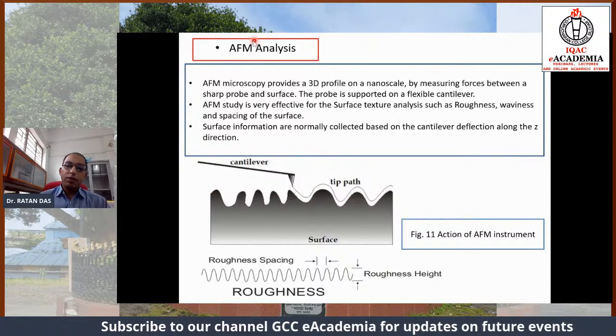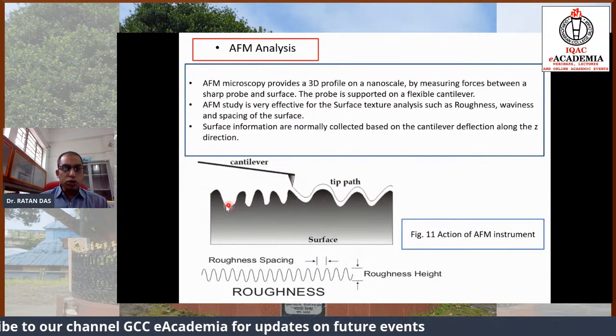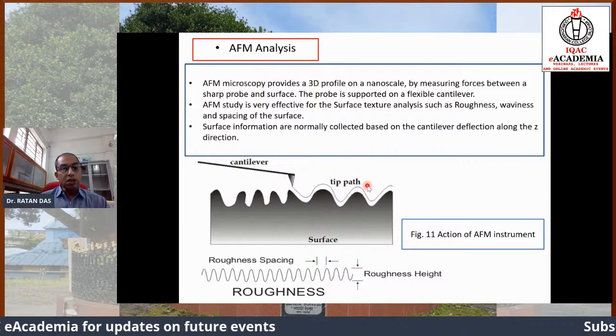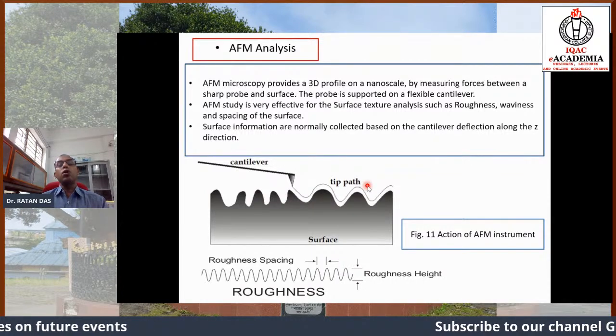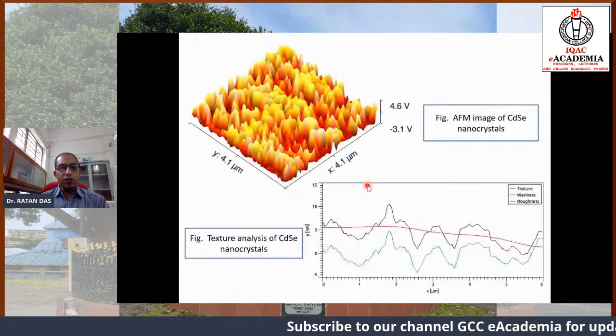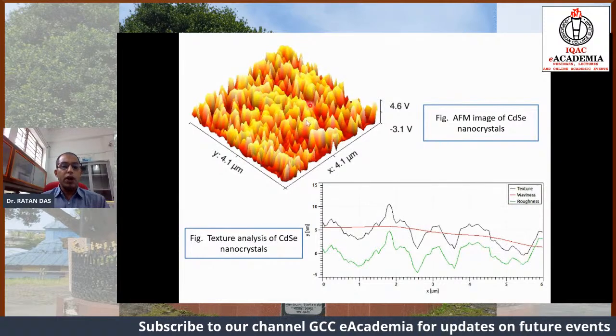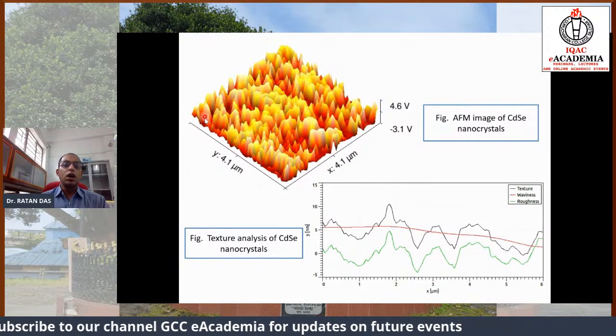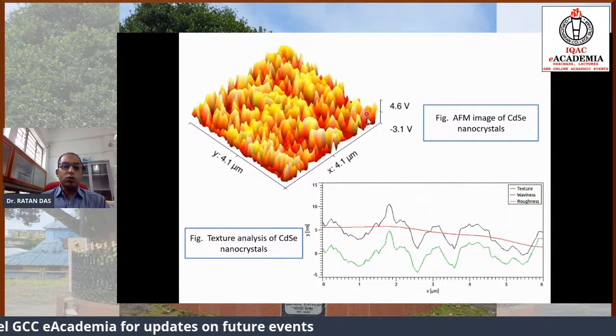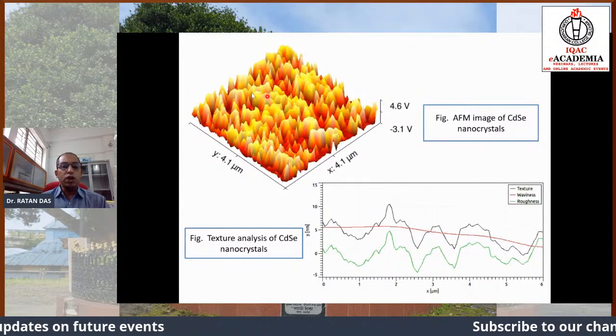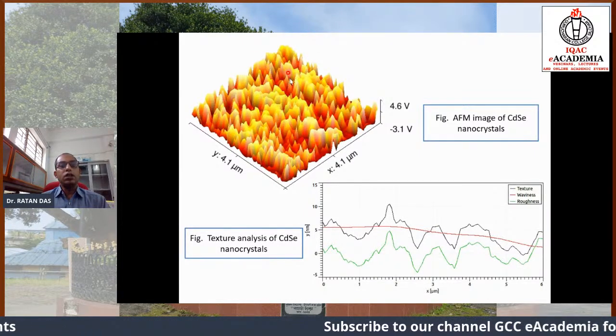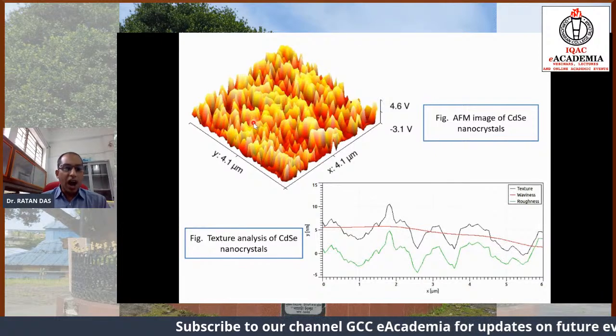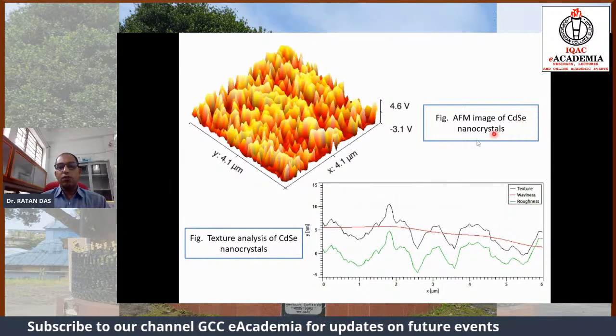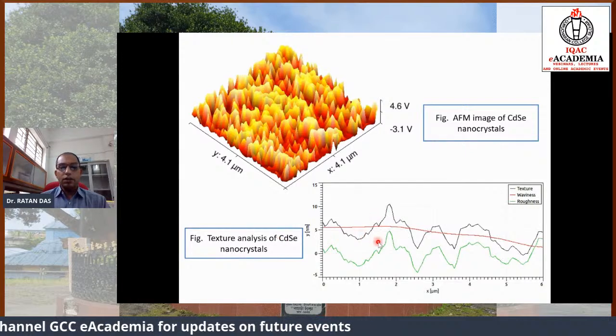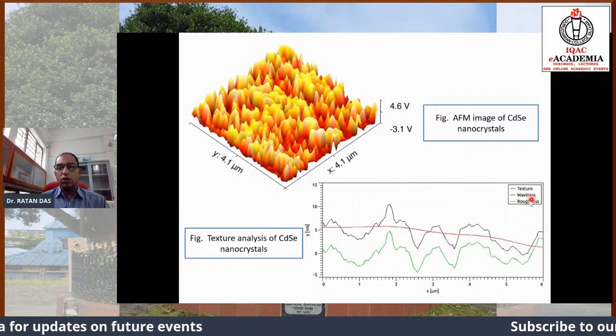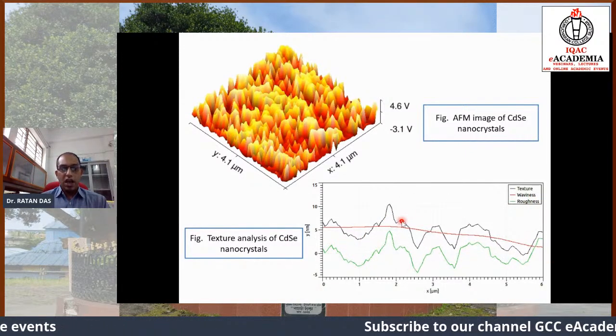Actually, AFM provides the smoothness or roughness of the thin film, but we also use it for nanoparticle surfaces. This is one example of our prepared nanocrystals, CdSe nanocrystals. You see the beautiful pattern that we have obtained, showing the height profile of the sample, the AFM image of CdSe nanocrystals. These are the height profile, texture and waviness that we have obtained in the AFM analysis.